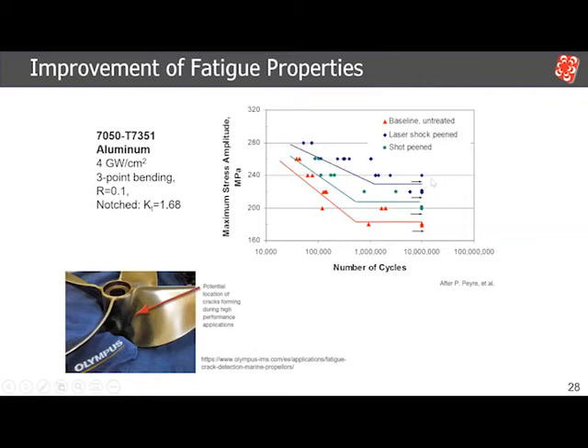Another way of looking at it is to take a specific number of cycles. Let's look at the endurance limit, which in this case is 10,000,000 cycles. Looking at the endurance strength, you can see the improvement generated by each of these surface treatments. The compressive stresses generated from the laser peening process, again, counteract your applied tensile stresses, pushing your entire SN curve up by lowering the net stresses experienced by the material. So the endurance limit is no longer down here at 180 or so. The compressive stresses are counteracting that stress and pushing your endurance strength up to 220 megapascal.